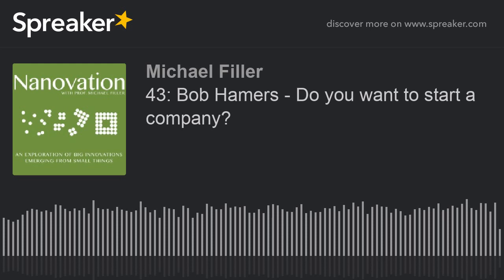If you look at what's happened in the lithium-ion battery field, these materials are pretty cheap. So cobalt can be expensive, but replacing cobalt with nickel and manganese to make these more complex materials, the so-called NMC materials, the driving force is to make the cost really, really low. And as you make the cost low, there's really very little economic incentive for recycling anymore. So then you get into this interesting question of understanding and balancing the potential environmental and health risks against the costs, for example, of recycling.